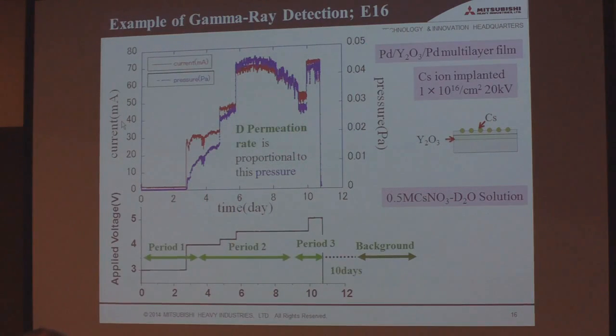This is an example of gamma ray detection, number E16. This is the experimental time, and this one is voltage. We usually start at 3 volts, then 4 volts and 5 volts, increasing the voltage, and correspondingly, the red one is the current. The current increases. And the blue one is pressure, which corresponds to the D2 permeation rate. At first we have a very small D2 permeation rate, and if we increase to a larger voltage, we get a large permeation rate. In this case, we use the palladium Y2O3 palladium multilayer thin film.